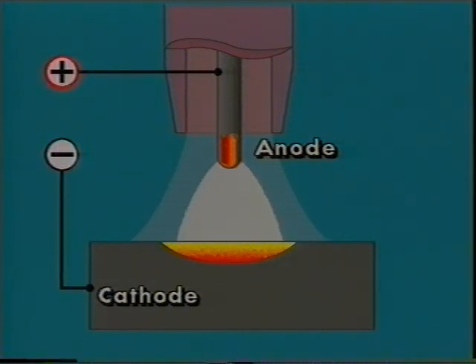With DC electrode positive, the electrode is positive and the workpiece is negative. This mode can be used for welding aluminium using pure helium as the shielding gas, where the helium arc has greater energy, and the action of the positive ions moving towards the workpiece disperses the tough refractory oxides of aluminium, which exist on the surface of the workpiece. Since most of the heat is in the electrode, larger diameter electrodes are needed, and care must be taken to ensure the molten end of the tungsten electrode does not contaminate the weld pool.